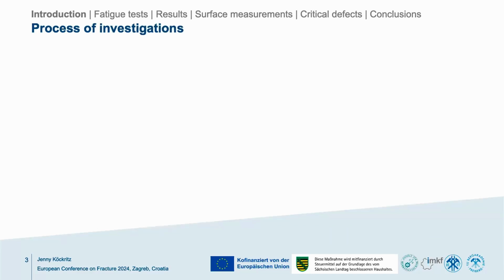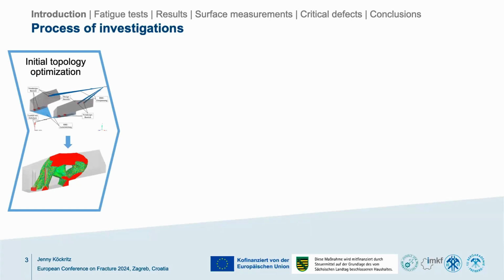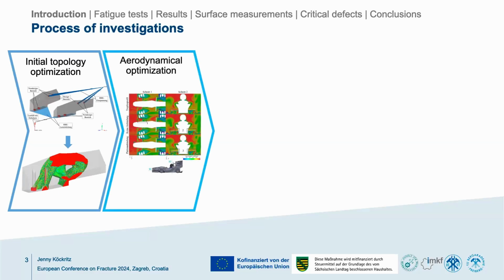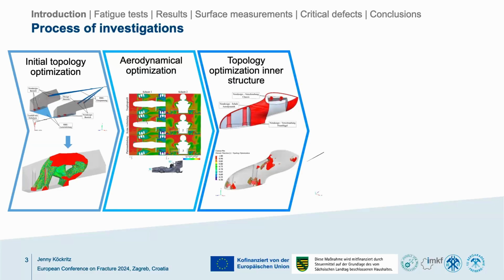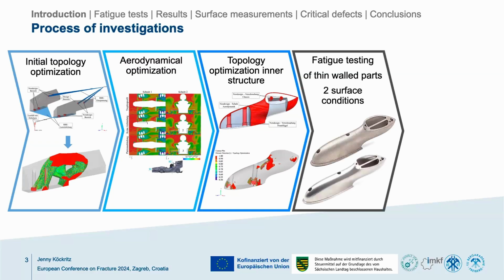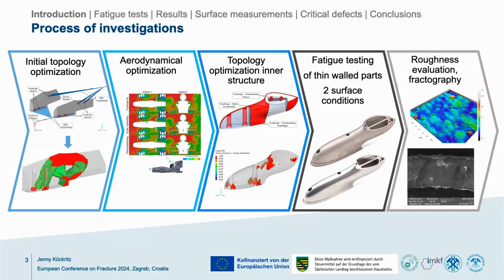I'm going to dive very shortly into the design process because this is supposed to be realistic. So first, we did an initial topology optimization of the design space. Based on that, we did an aerodynamical optimization of the outer shape of these parts. We used this outer shape as a starting point for the topology optimization of the inner structure. And the result were thin-walled hollow pieces, which have varying wall thicknesses and some inner structures for stiffness. We performed fatigue tests on these parts in 2 surface conditions. And also we did roughness evaluations and fractography after damage.